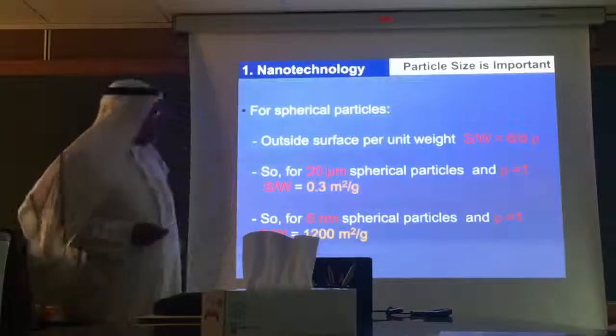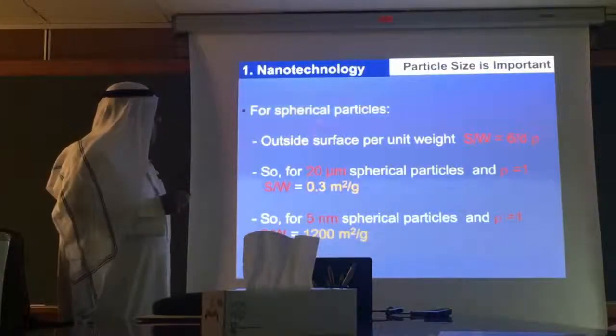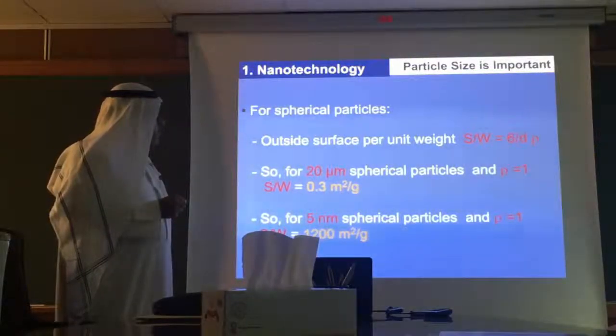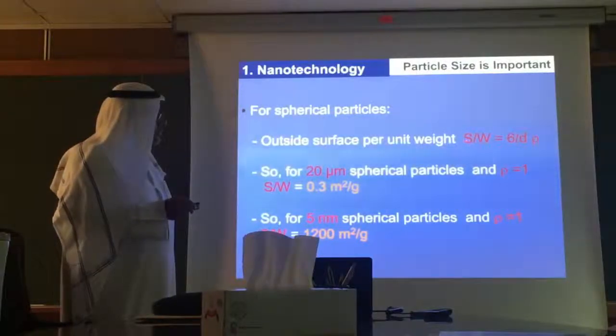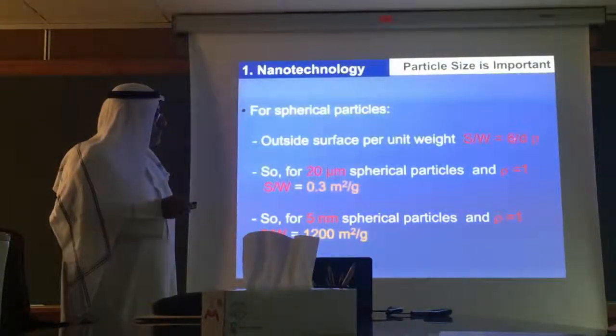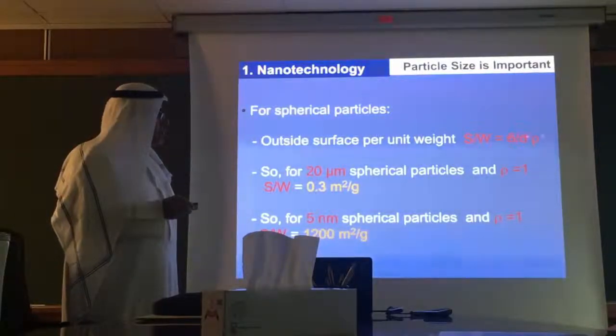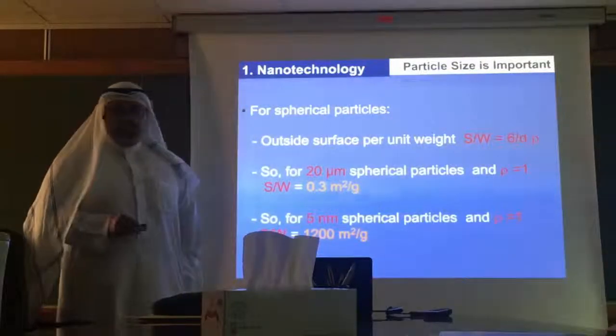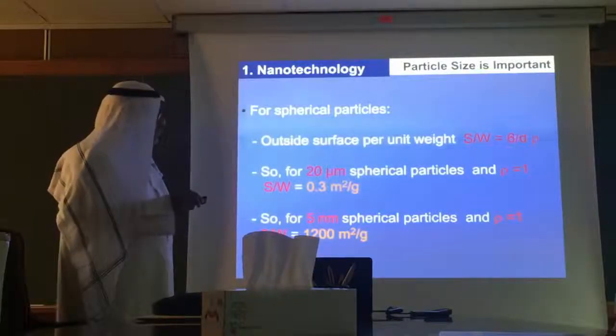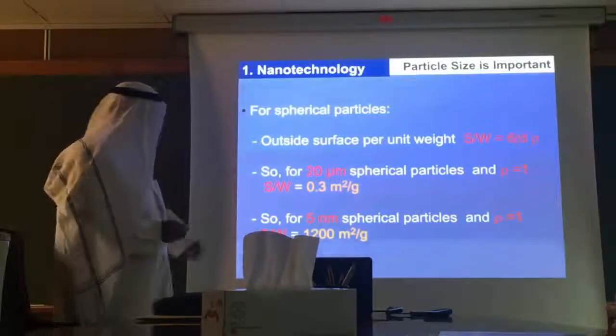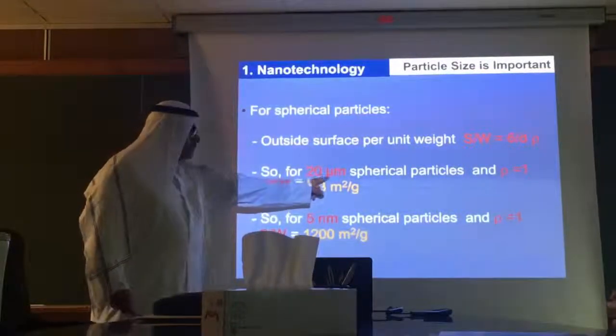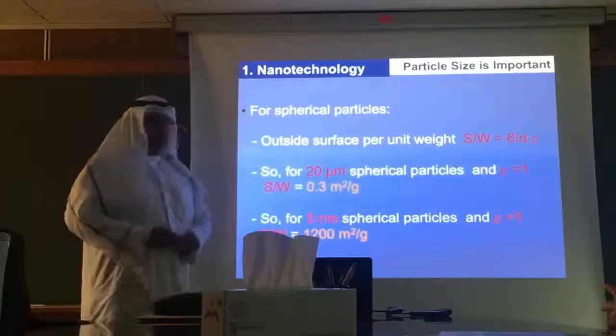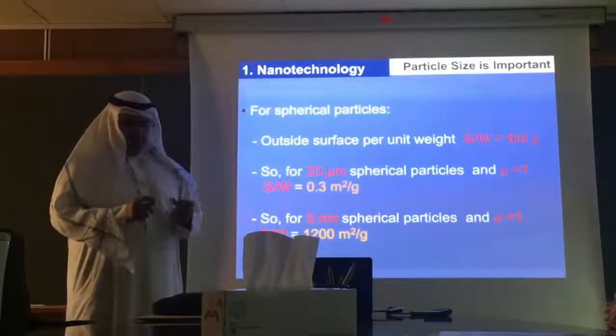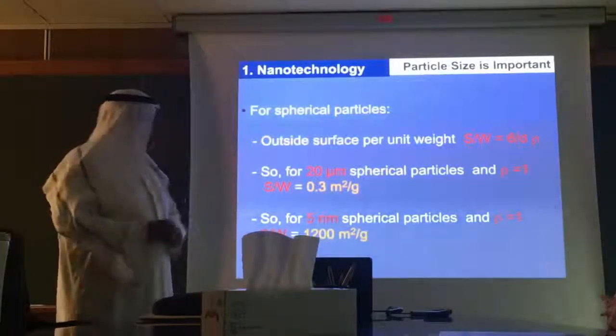Okay, so we know that for spherical particles, the surface to weight ratio, as we call it, you can get by dividing 6 over the diameter of the particles times the density. If you do this simple math, you'll find, for example, for 20 micrometers, this is not nano size, 0.3 meter square per gram.